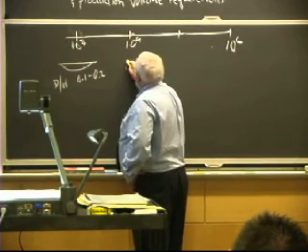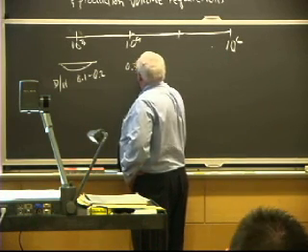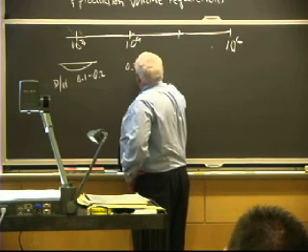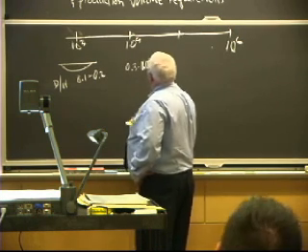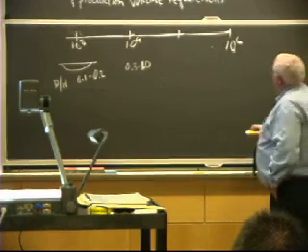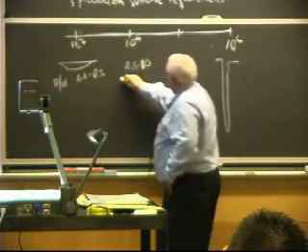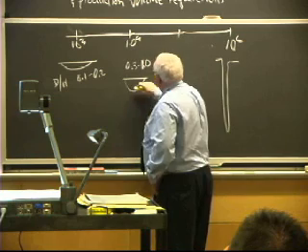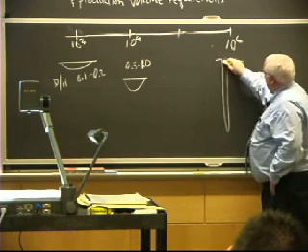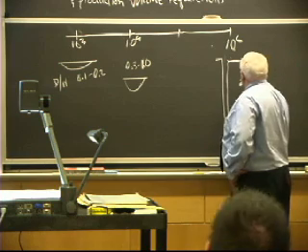Here you'll have something on the order, theoretically 0.5, but it's going to be 0.3 to 1.0. It turns out you can actually get something deeper than a hemisphere for other reasons we'll talk about later. And over here, it turns out you can get a depth to width ratio, so this one might be something like that. The depth to width ratio for a laser or electron beam, where we're essentially doing hole drilling, people have actually done 200 to 1.